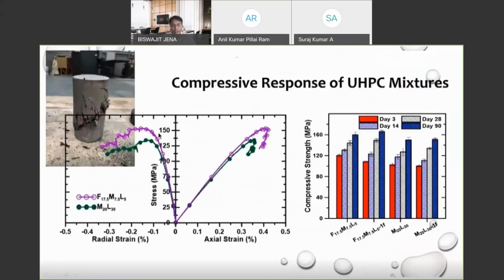So next, here is the complete axial stress and axial strain and radial strain curve for non-fiber reinforced ultra high performance concrete. So you can see the maximum strength is 150 megapascal. The maximum axial strain is about 0.35%, which is basically the maximum allowable strain of concrete in the design. So the first understanding is that ultra high performance concrete does not change the maximum axial compressive strain capacity of concrete in the unreinforced state, or without a reinforced state. The strength, as we can see, is up to 160 and 170 megapascal, depending on the kind of mix. So you will see the failure pattern of the mix right here. Again, very high strength mixes fail in this fashion, as you would have seen.